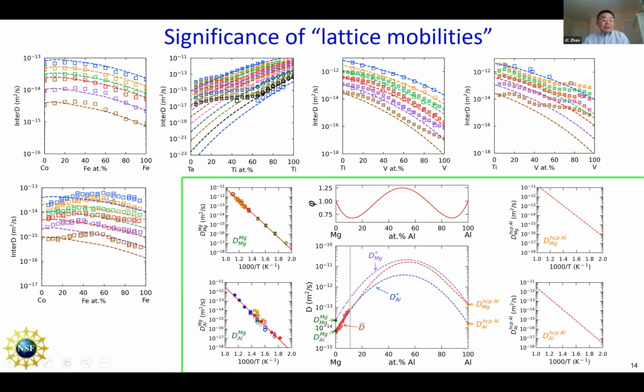But if you look at the data for the interdiffusion coefficient in this one, on this side it does not agree with the impurity diffusion coefficient. On this side it does not agree with this. So if you forcefully fit those data, you use a lot of parameters, and it is not going to give you anything good. Because if this does not agree, that's not good data to use.